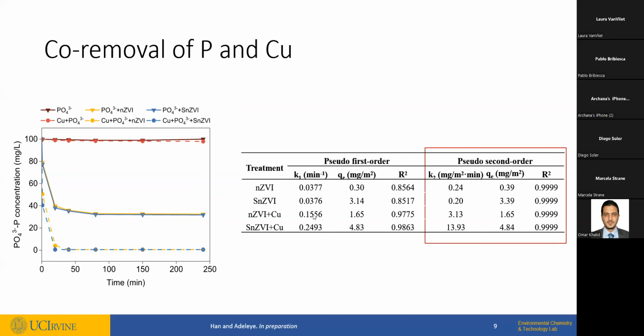So to put some numbers to what we are looking at, we model this result using the first and second order kinetics models, and we see a better fit with a pseudo second order kinetics model. Right over here, you can see the capacity of the nanoparticles for the two contaminants, and particularly when there is copper present in addition to phosphate, we see the capacity for removing phosphate is really high.